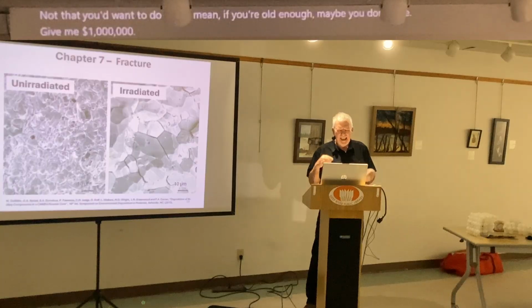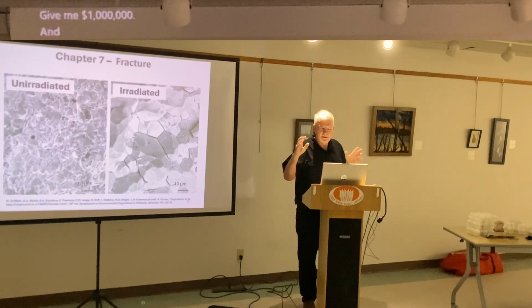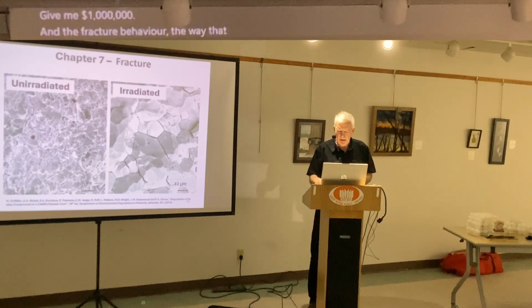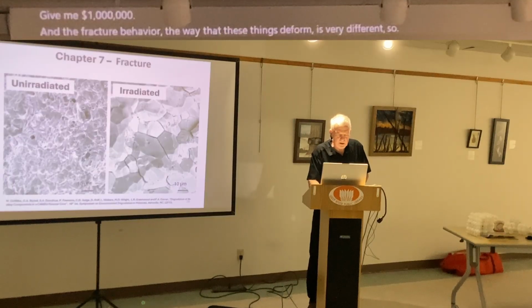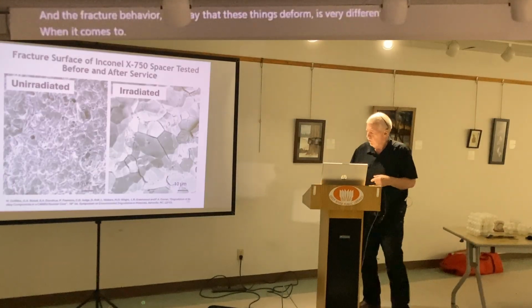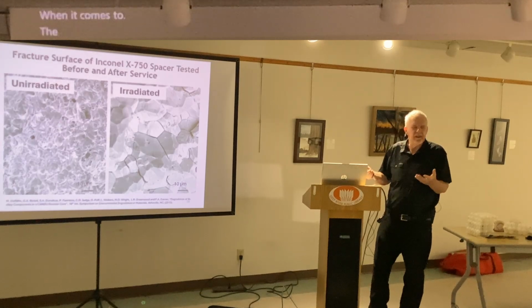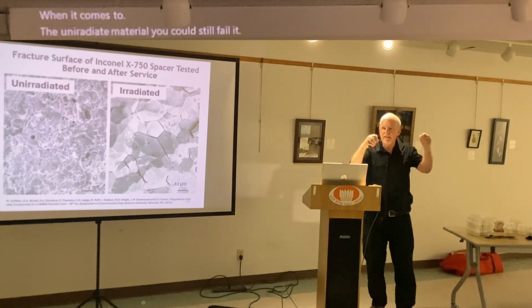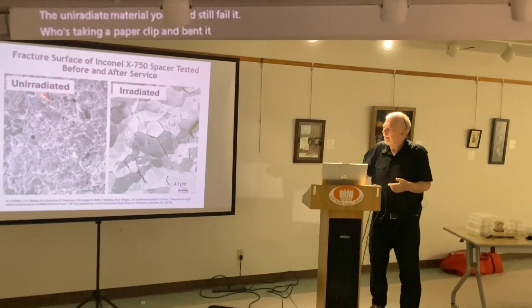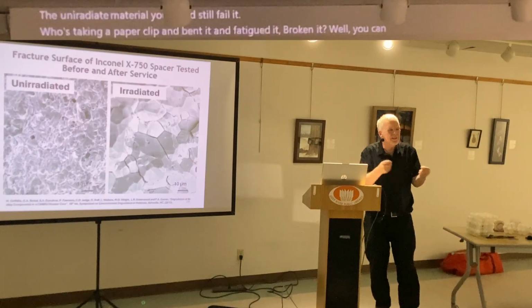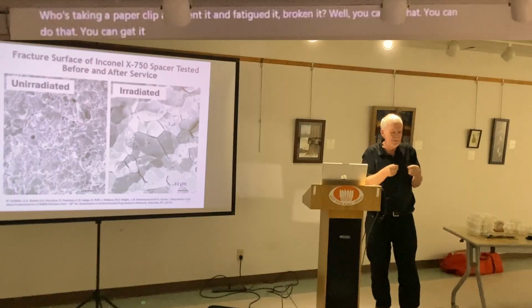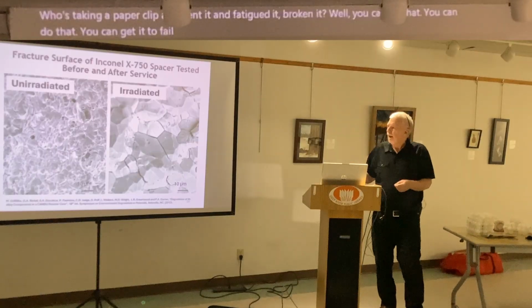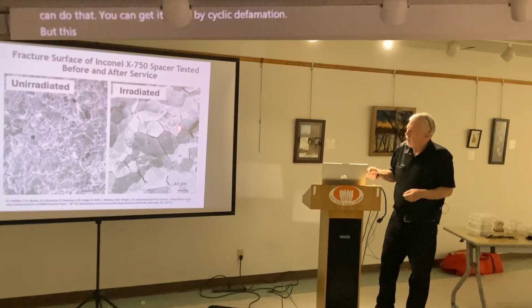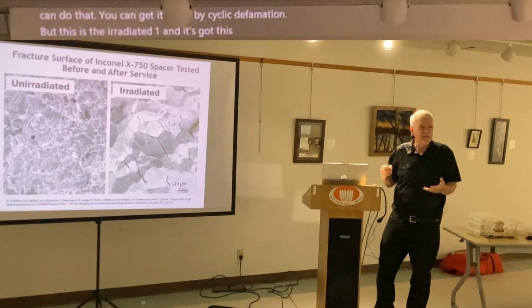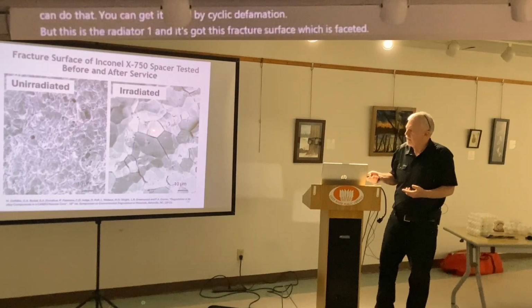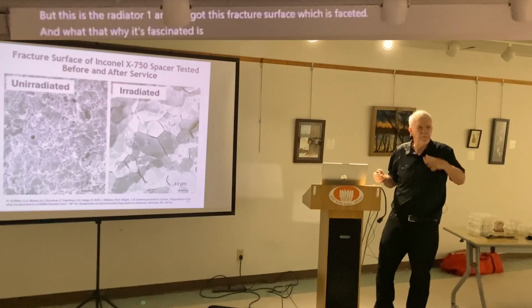Anyway, the fracture behavior, the way these things deform, is very different. With the unirradiated material, you could still fail it. Who's taken a paperclip and bent it and fatigued it and broken it? Well, you can do that. You can get it to fail by cyclic deformation. But this is the irradiated one, and it's got this fracture surface which is faceted. And why it's faceted is because those represent the boundaries of the grain.